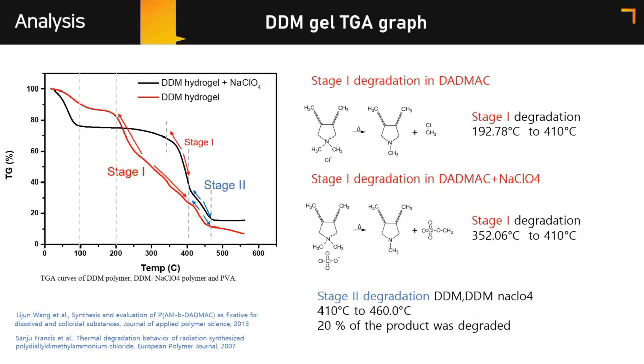In the first stage of the hydrogel degradation, a methyl group of DADMAC is decomposed and binds with the Cl- anion to produce CH3Cl. Similarly, in the hydrogel with NaClO4, the ClO4 anion binds with the methyl group of the DADMAC. The last degradation took place at 410 Celsius to 460 Celsius, and DDM and DDM ClO4 polymer were degraded 20%. It was confirmed that the decomposition temperature changed according to the salt's anion.